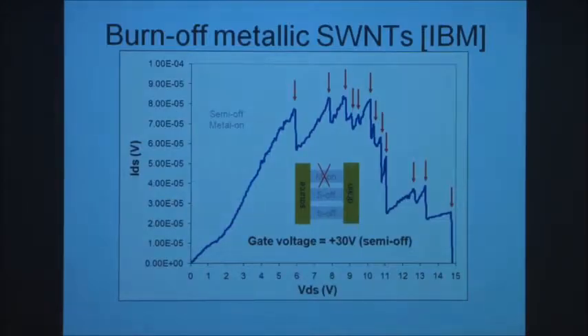So IBM were very, very clever. What they did is they assumed they had a bunch of semiconducting and metallic nanotubes between the two contacts. So they bias the back gate to switch off all the semiconducting nanotubes. And then they passed the high current through it, and it just blew up the metal ones. It was just like a fuse. And so you can see in this case, there was 1, 2, 3, 4, 5, 6, 7, 8, 9, 10, 11, 12 metallic nanotubes. They'd just blown them all up.